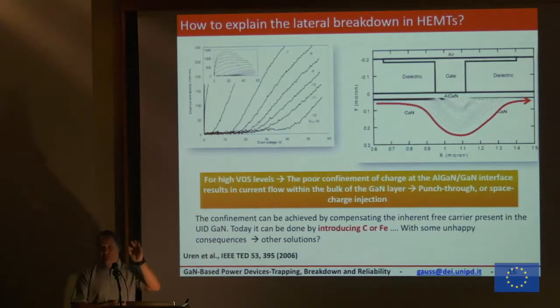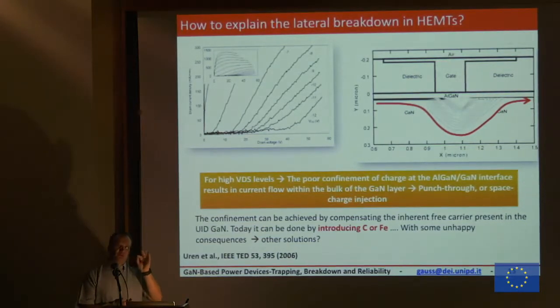This is an extremely important point for two reasons. First of all, I am introducing deep level traps. Okay, so if I am able to do the process very well, understanding very well how this profile of this doping can be done at which temperature, then I do a perfect compensation. And then my layer becomes insulating, and then my device can have a very good breakdown. But this is not always the case. If I do not grow very well and do not introduce these two elements very well, I just introduce traps. So not only am I not able to compensate the free carrier, but I am even introducing traps that will provoke the problem of the trapping and the instability I will speak to you about later.